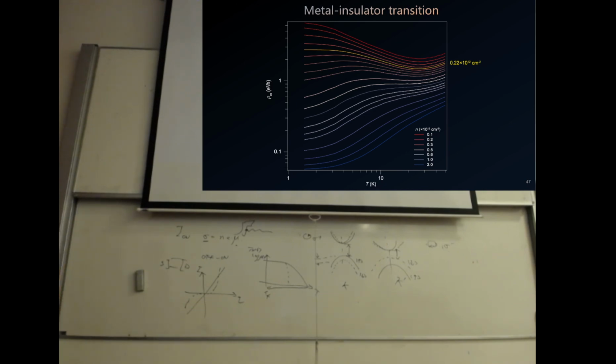Supposedly, according to mesoscale physics, this thing should be like e square over h. It's somehow slightly higher than that. It's probably due to the estimation of aspect ratio of the sample. Anyways, it's very close to what it's supposed to be. And this is a measure of the general properties of this sample.